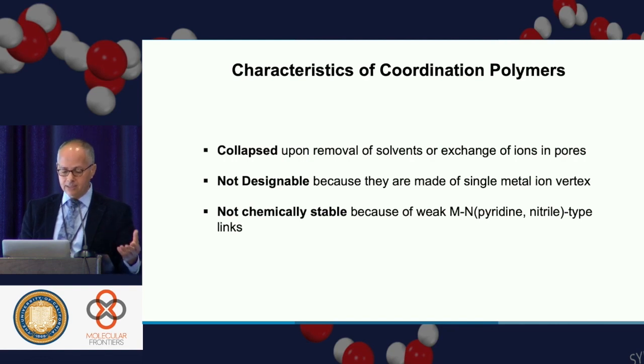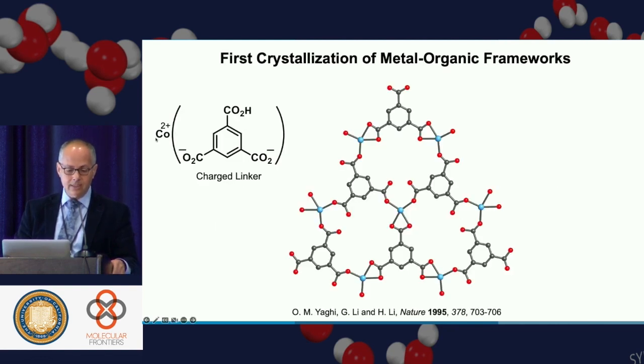And so, trained as an inorganic chemist, I immediately realized that you could take metal ions, and now, instead of neutral linkers, you can have charged linkers. And if you choose carboxylates, not only can you strengthen that interaction, in fact, a cobalt 2+ carboxylate bond is a very strong bond, almost as strong as some of the organic covalent bonds. But we illustrated that you could take, for the first time, an anionic organic linker, and link it up with cobalt and make a crystal. This was the first illustration. I would say this was the beginning of what, in those days, I called metal organic frameworks, and now people call MOFs.